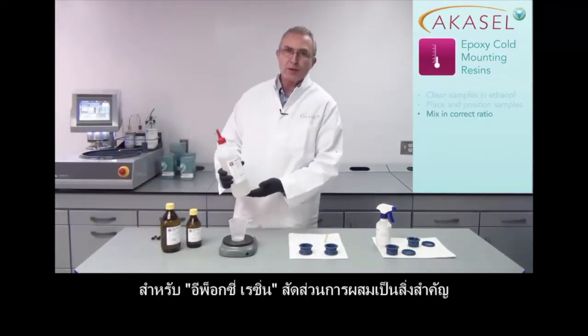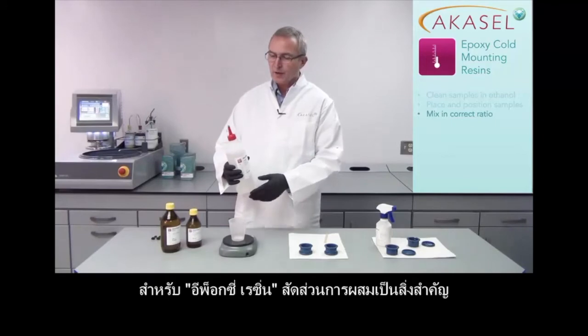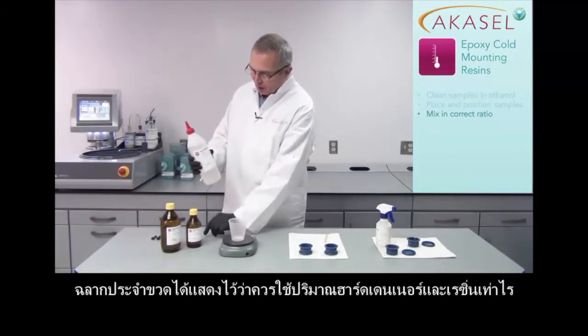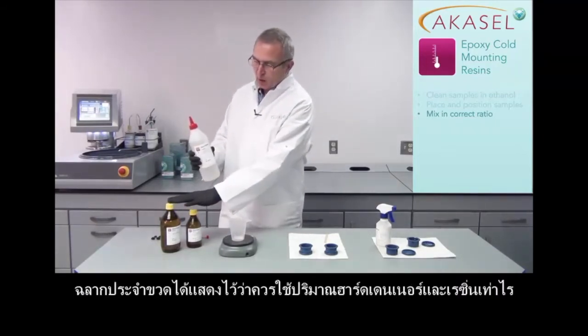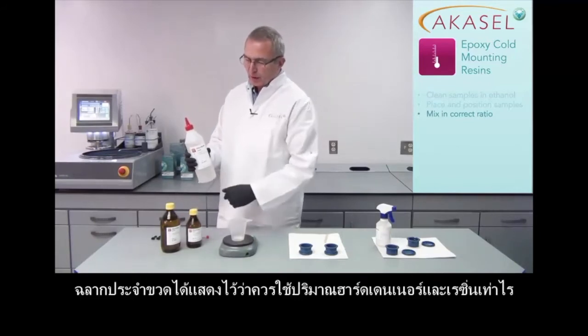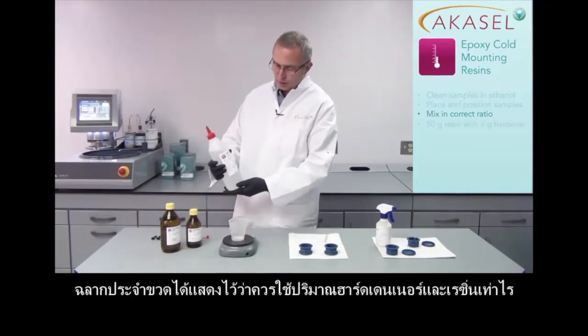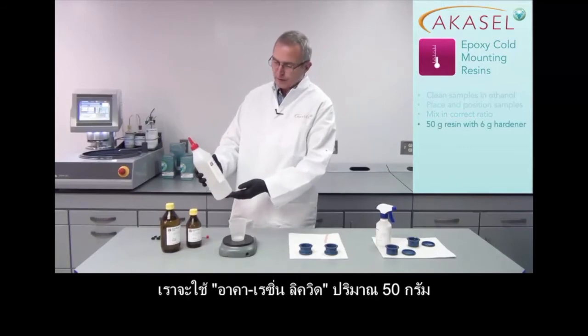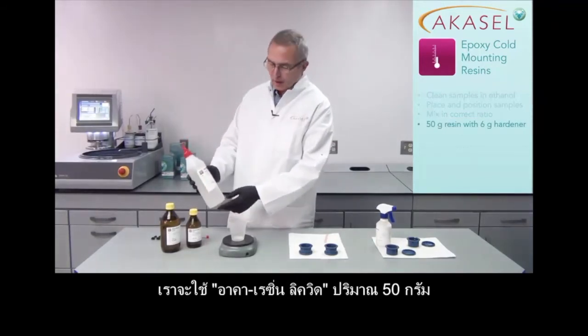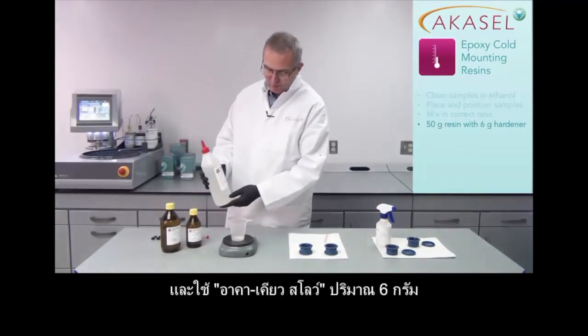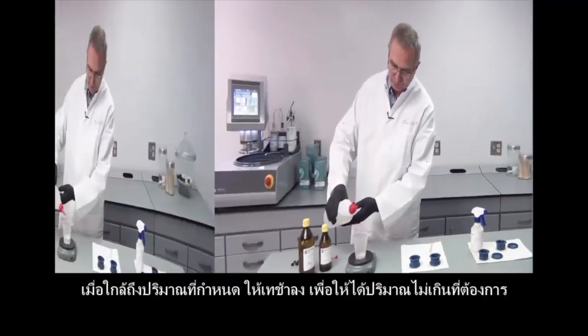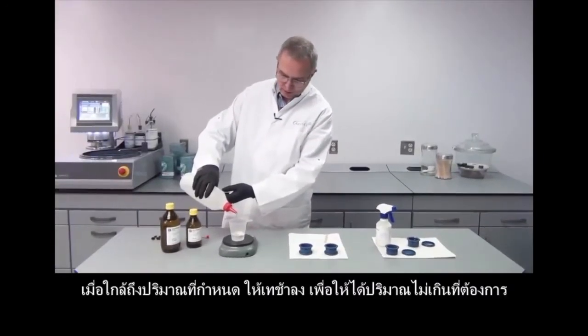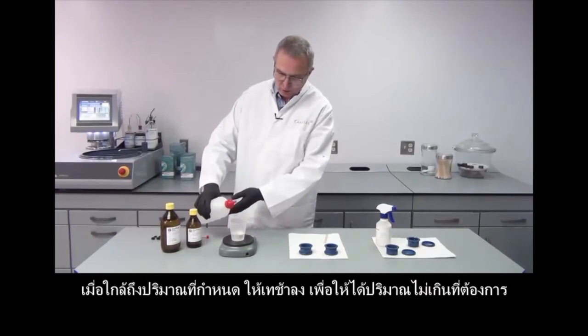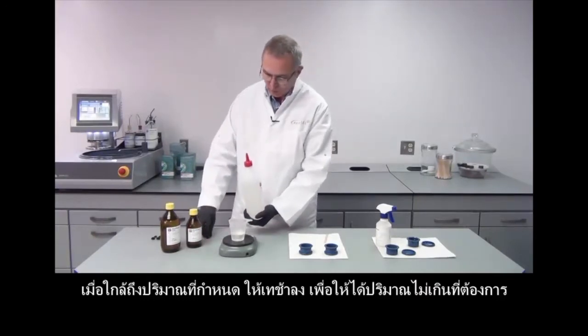With the epoxy resin, it's very important to mix it in the correct ratio. On the label it says how much of either the hardener should be used together with the resin. In that case, we're using 50 grams of the Aka resin liquid, and we will be using 6 grams of the Akacure Slow. Towards the end, when I'm getting close, I'm going slower to not overdose.